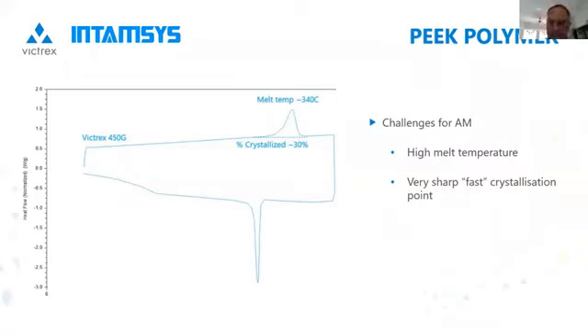So why did we think re-engineering the polymer would help? Well, as I mentioned with semi-crystalline PEEK, the current challenges for 3D printing can be seen here in this DSC trace, which shows how the standard PEEK polymer behaves. Along the top of the trace, you can see it melts at about 343 degrees Celsius, which is 649 Fahrenheit. So a high temperature for a polymer. And then along the bottom of the trace, it recrystallizes rapidly at around 297 Celsius. So this happens fast and doesn't really allow layers much time to bond.